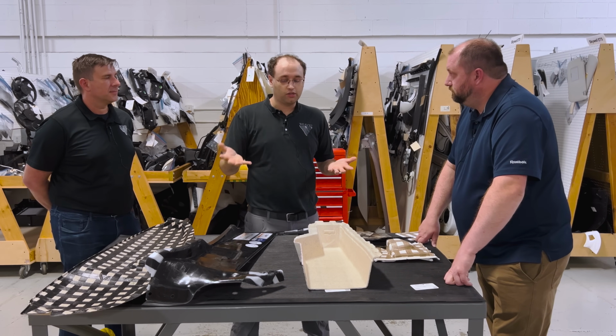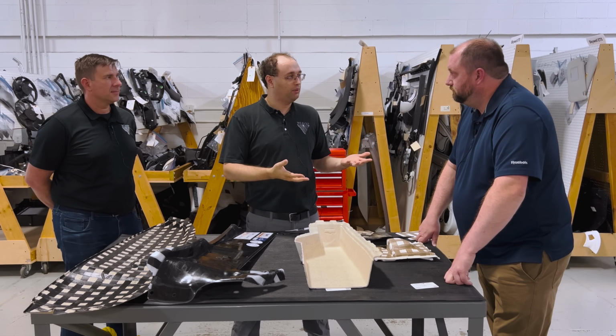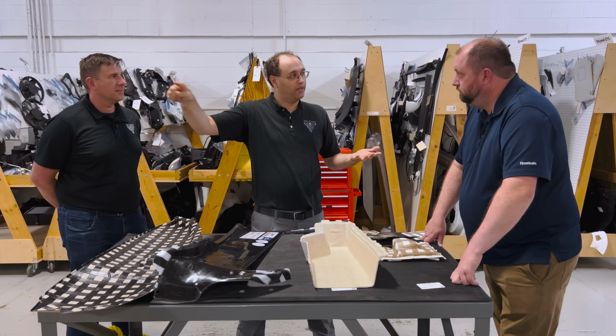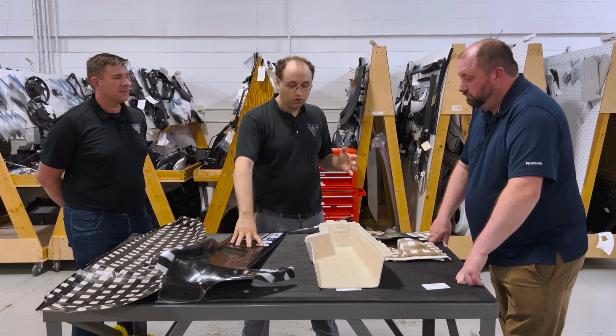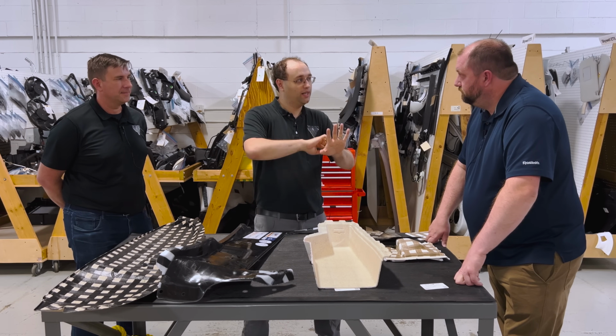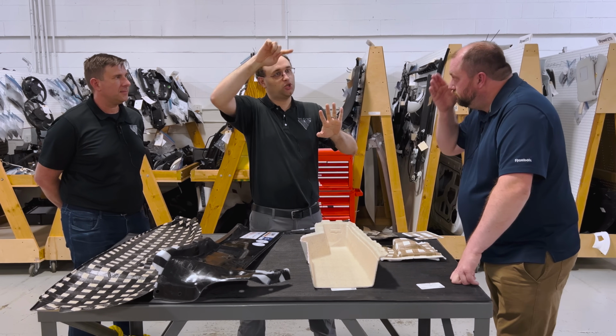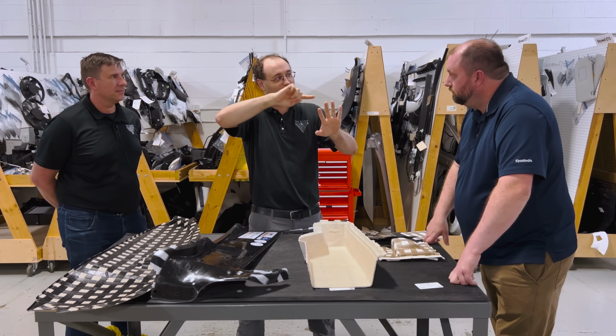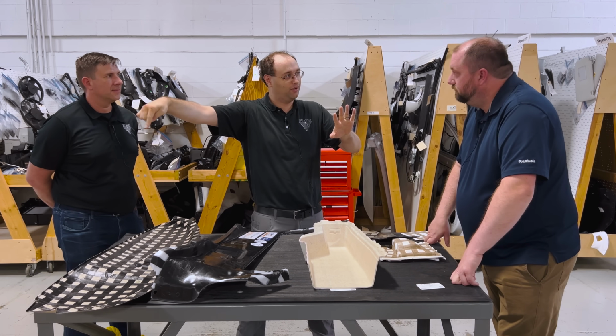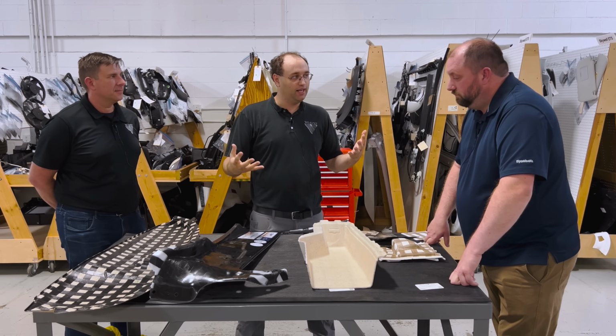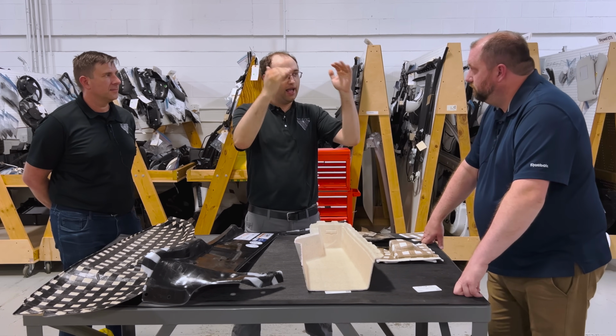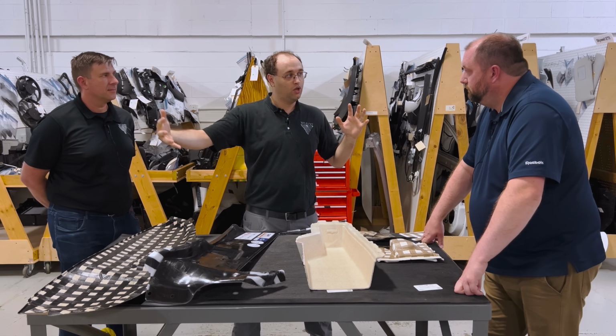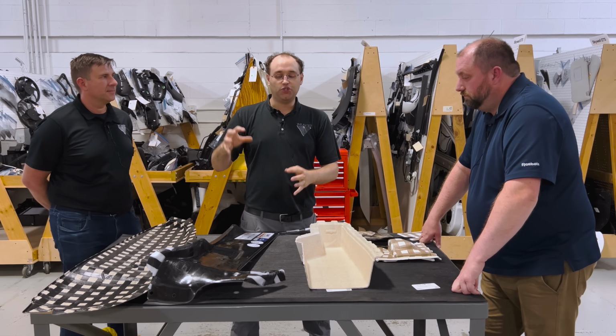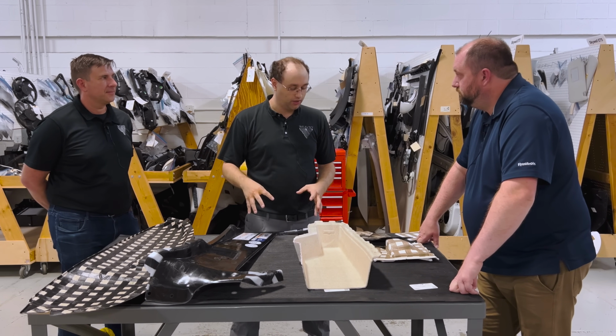If you look at a traditional stress strain curve for injection molded plastic, it's kind of this long curvy bit. If you combine these two, you actually get both. You get a straight portion, then a bunch of cracking, then it drops down to a plateau and stays there for a really long period of time. So what you're effectively getting is high stiffness, high strength, and high toughness all within one package, just by tailoring your relative mix of materials.